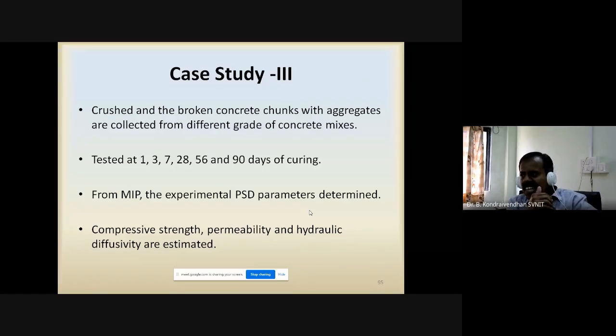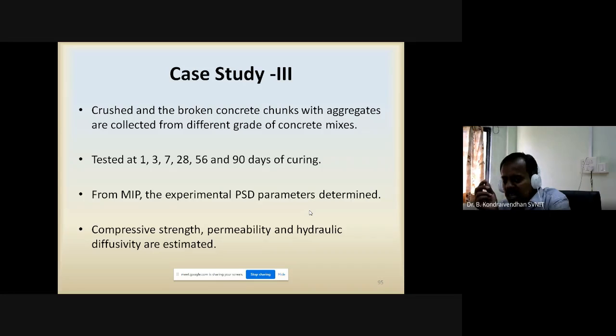Here you can see, he has not cast the sample, because in concrete the size is very small, so we have to take a core. But instead of taking a core, he has used crushed chunks of the aggregate with cement matrix. That's what he used here.